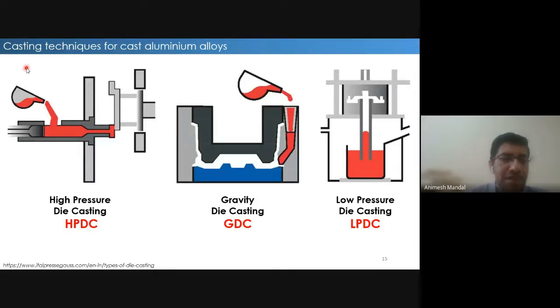One is high pressure die casting, called HPDC in short. Here you have the liquid metal poured into a shot sleeve, as we call it, and it is rammed into the die at a very, very high pressure and fills the die. This is a very popular technique for producing components on a large scale. That means you do not produce a few hundred components using this. Generally, you want to produce millions and millions of components.